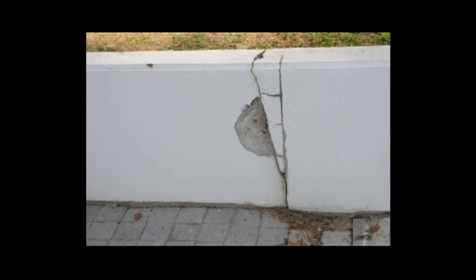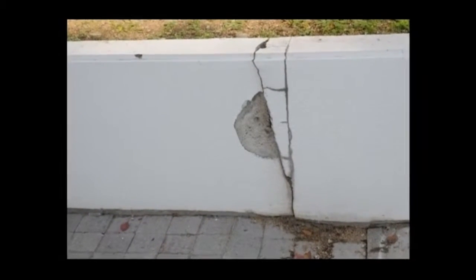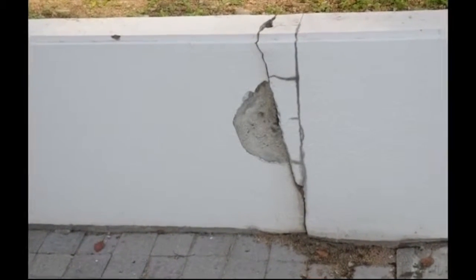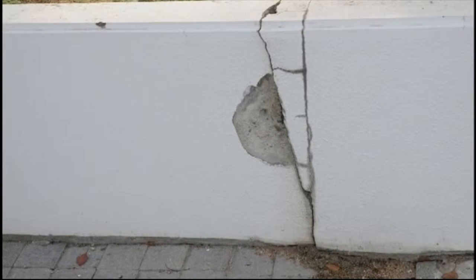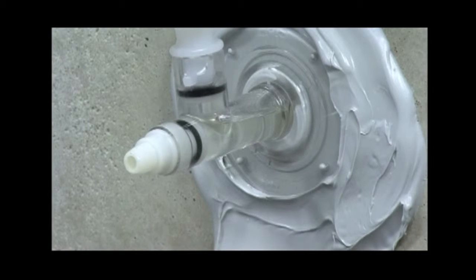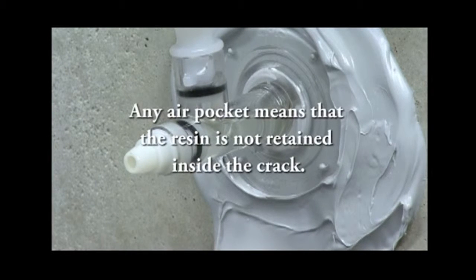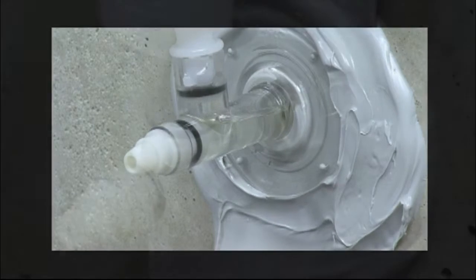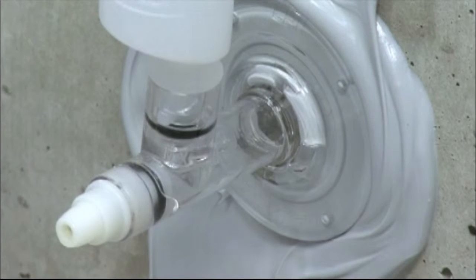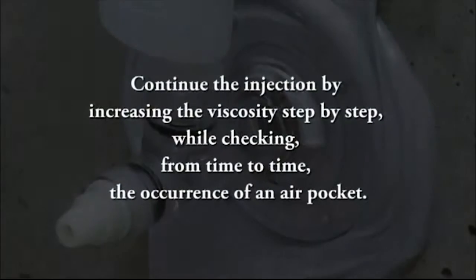If there is a so-called penetrated crack, which is cracked through the entire depth, and its rear side cannot be completely sealed, then resin of low viscosity will flow down to the bottom of the crack and run out of the rear void. Everbond EP400 is a resin of super low viscosity, and the pressure tank is soon emptied at a large crack. Therefore, the resin's viscosity needs to be gradually increased until the resin will not be flowing down inside the crack.